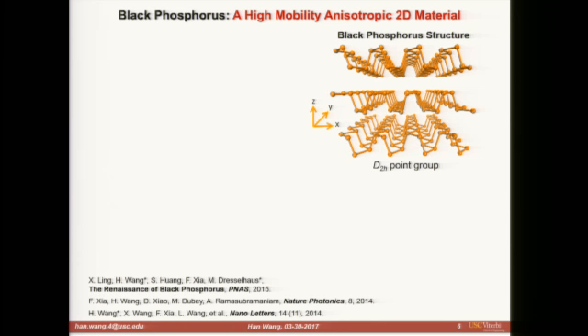However, because phosphorus is a group 5 element, it has 1 extra valence electron compared to carbon in graphene. This gives rise to a puckered orthorhombic structure, where within each layer of BP, the phosphorus atoms stay on 2 separate planes, going up and down.